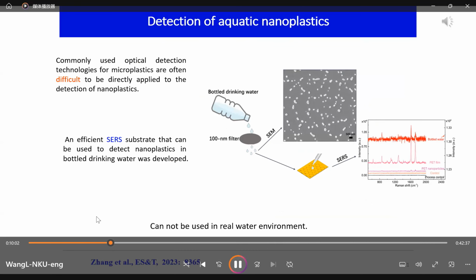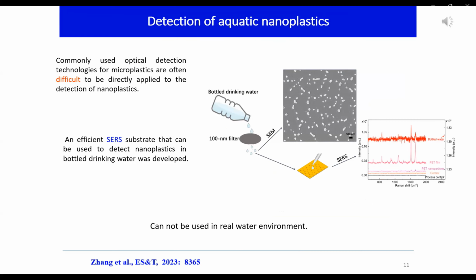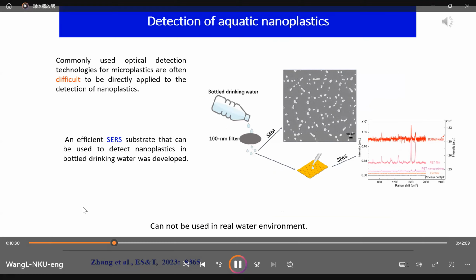Raman enhanced material that can significantly enhance the Raman signals. The bottled water can be analyzed directly after filtration with 100 nanometer filters without any further treatment. However, the method selectivity is poor because this method doesn't analyze the individual particles. So if there are multiple types of particles coexisting, this method cannot work.